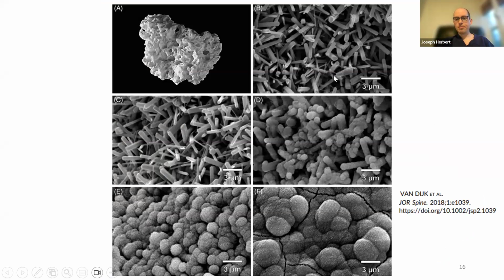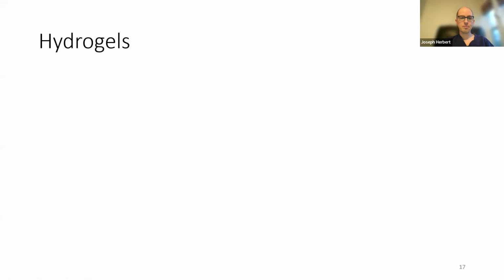But just like with porous titanium, for whatever reason, when you start modifying the structure on a nanoscale level, and it's rough or porous or kind of needle-like, that does seem to have a pretty big impact on how the body reacts to it and how bone in particular grows onto it. So when you take tricalcium phosphate, which in and of itself does induce bone growth, or hydroxyapatite, which is relatively inert, and you mix those two things together, it's not just the composition of the graft that matters. It also depends on the microscale or nanoscale structure of what you're using.